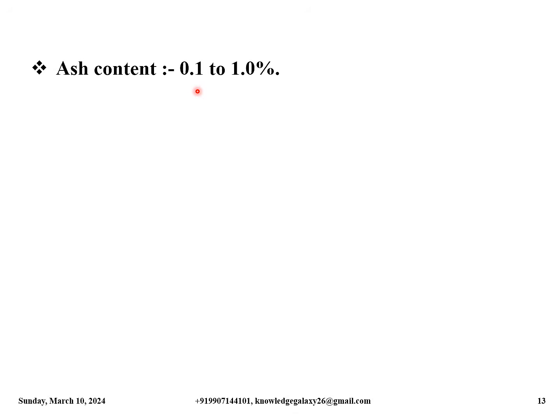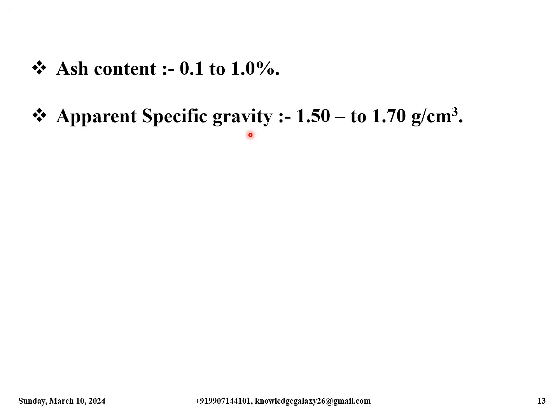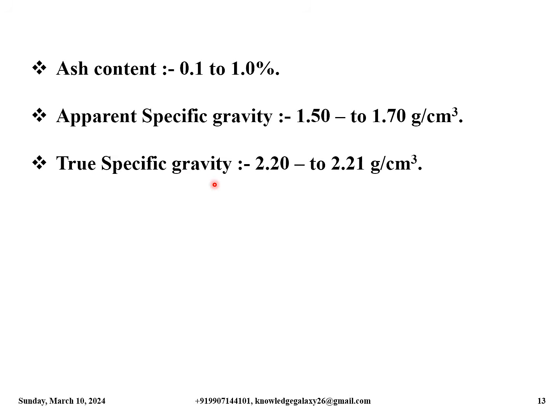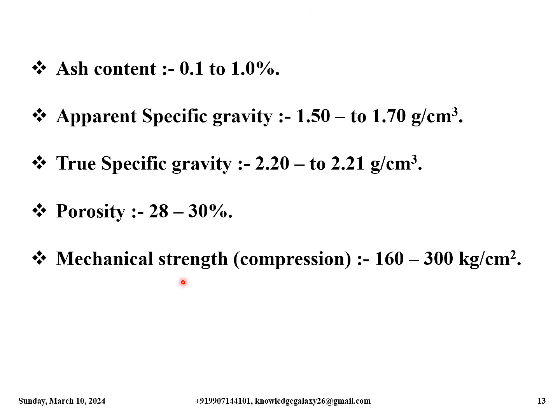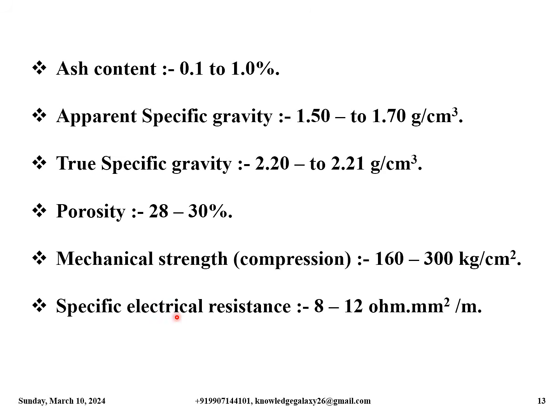First, ash content 0.1 to 1.0%. Next, apparent specific gravity 1.50 to 1.70 gram per cubic centimeter. True specific gravity 2.20 to 2.21 gram per cubic centimeter. Porosity should be 28 to 30%. Mechanical strength in compression should be 160 to 300 kg per square centimeter. Specific electrical resistance should be 8 to 12 ohm millimeter square per meter.